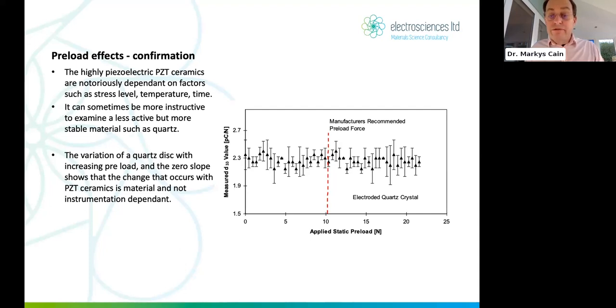When you do the same experiment for quartz, you see no difference at all. So static preload, measured d33, 2.37. You see very little variation. I mean, it's just experimental error really here in the value of quartz. Now, quartz is not ferroelectric, it's just piezoelectric. So you wouldn't necessarily expect to see such a variability, such variation in piezo response as a function of preload, for example, applied to the material, or voltage applied to the material, and that's what we do see.